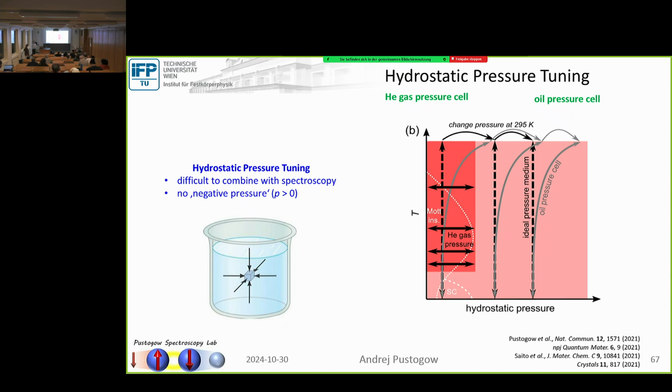Because ruby does change at pretty high pressure, so I am aware that, for example, samarium crystals are more sensitive for the lower region of the pressure. I believe different groups are using different things. One setup I know they used ruby, but yes, certainly others can be applied. And at very low temperatures, one could use something like the superconductivity of tin, for instance, because this is also pressure sensitive, but many choices.